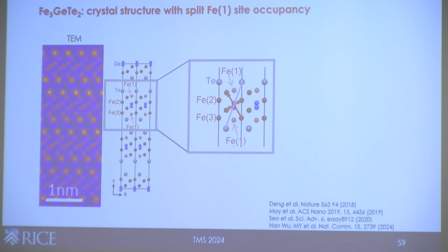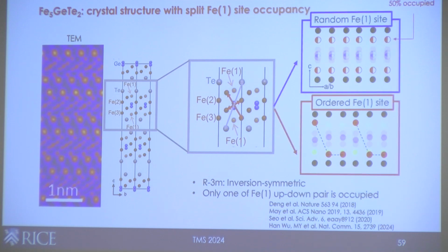And it's interesting that people have realized that this crystal actually can be stabilized in 2 structures. And in one structure, between each up-down pair, it'll randomly choose to occupy the up one or the down one across the crystal. So there's no correlation between which one is chosen. So in essence, locally it will choose one of them, but on average, you can consider each one being 50% occupied. And you can see that this structure is still inversion symmetric globally.